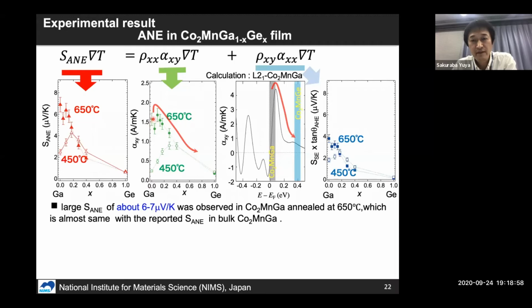We speculated that this discrepancy is due to a Fermi-level shift due to the off-stoichiometry of our Co2MnGa thin film. But anyway, we clearly see the reduction of alpha XY with increasing germanium composition, as this theory predicted.